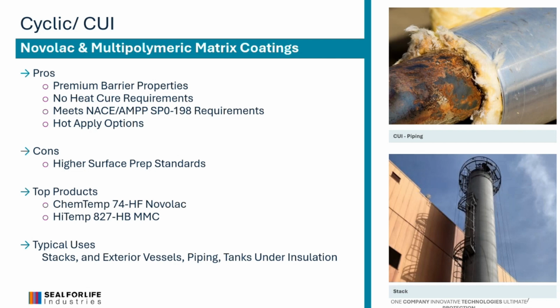Our top products here are ChemTemp 74 HF Novolac. That would be good to 350 degrees with excursions up to 400 degrees. This is also an immersion grade product and can take immersion cargoes up to 350 degrees as well. Our HiTemp 827 is our multi-polymeric matrix coating. This particular product is different than a lot of high heat coatings that are out there. Most high heat coatings people are familiar with are thin film coatings, so they are flexible enough to move with the substrate. The 827 HB can go up to 16 mils in a couple coats to give you the corrosion protection as well as the high heat capabilities. Typical uses here are stacks, exterior vessels, piping, tanks, and under insulation.